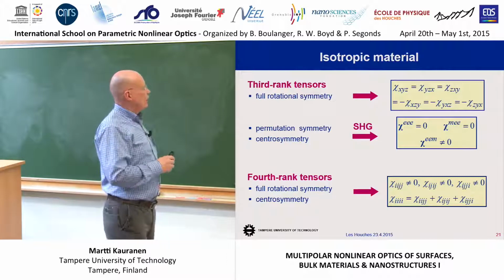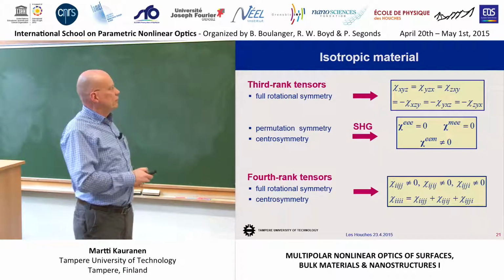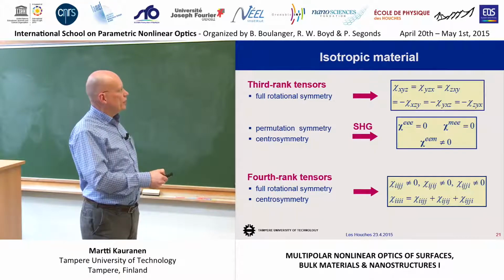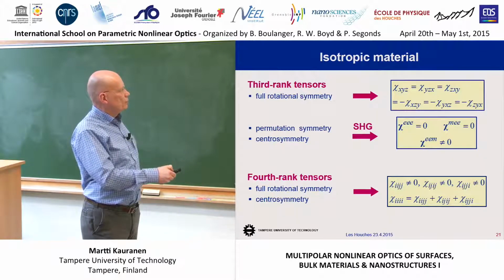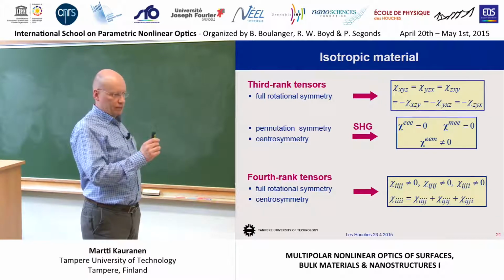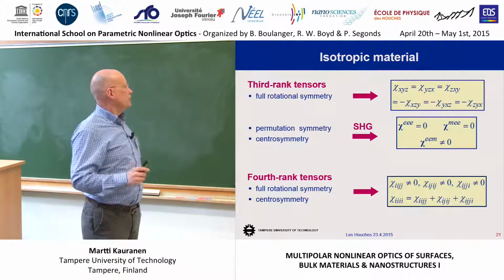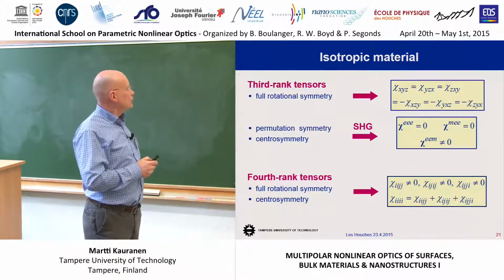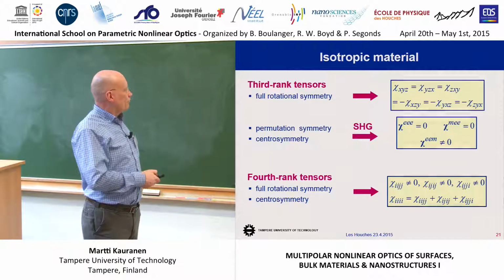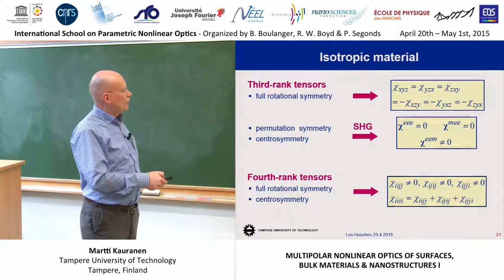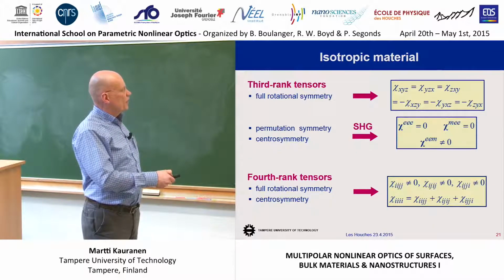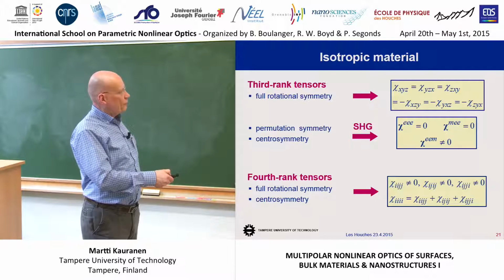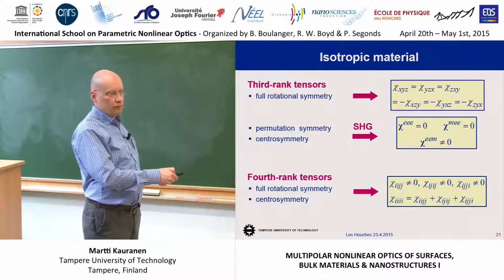This means that if you look at second harmonic generation, where you have to take into account the permutation symmetry, then these two have to be equal because of permutation symmetry, so the whole response is killed. So no second harmonic generation in isotropic materials. And of course you can kill this also because of centrosymmetry. MEE, we can require that this tensor has permutation symmetry in the two last indices, which are both related to electric-dipole interactions. We can kill also this tensor.